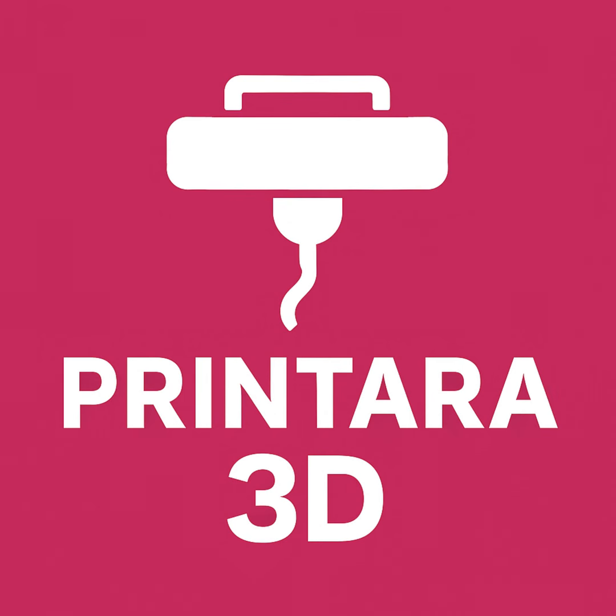We have to manipulate the thermal environment. You cannot just put a cardboard box over the printer and hope for the best. No, you definitely cannot. You need an active or at least heavily insulated chamber sitting at a sustained 35 to 45 degrees Celsius and a bed cranked all the way up to 100 or 110 degrees. That ambient chamber temperature is the key. By keeping the air surrounding the print at 45 degrees, you slow down the cooling rate of the upper layers. You minimize the extreme temperature delta between the hot bed and the cool top. This allows the polymer chains to relax slightly as they cool, significantly reducing that internal pulling stress.